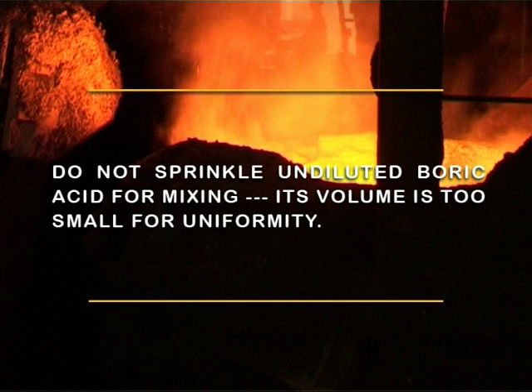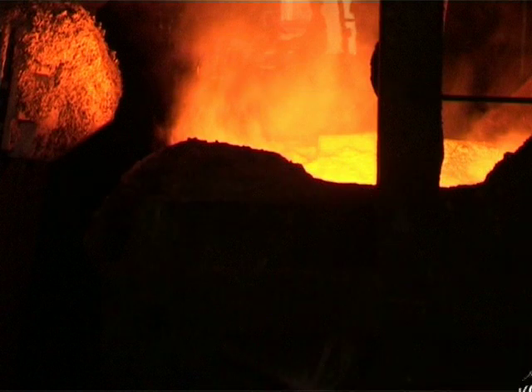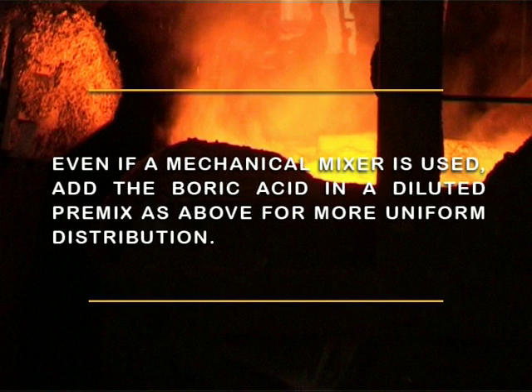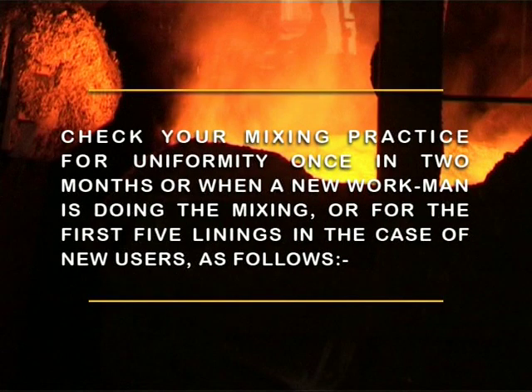Do not sprinkle undiluted boric acid for mixing. Its volume is too small for uniformity. Even if a mechanical mixer is used, add the boric acid in a diluted premix as shown for more uniform distribution. Check your mixing practice for uniformity once in 2 months, or when a new workman is doing the mixing, or for the first 5 linings in the case of new users, as follows.